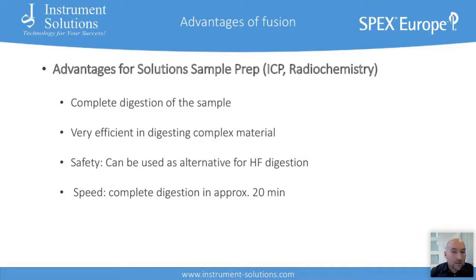Advantages are that it's a complete digestion of a sample, which is often not the case when using concentrated acids. It's very efficient in digesting complex materials that are difficult to digest with acids. It's very safe, and can be used as an alternative for HF digestion. And it's also very fast. Complete digestion takes approximately 20 minutes, but sometimes it's even shorter. And this is from the start to a cooled bead or a cooled solution.